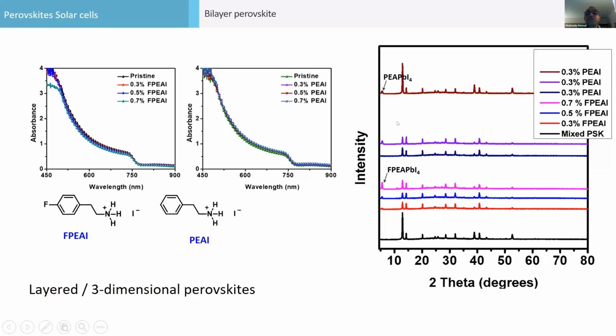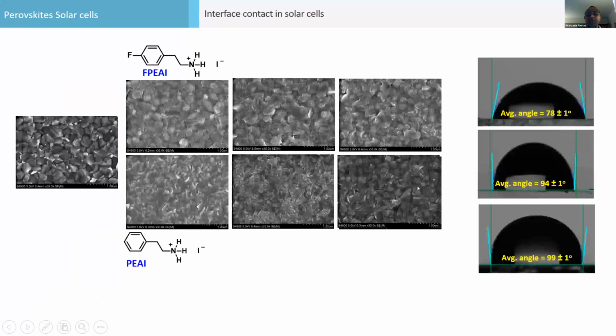Sorry. And also it formed PbI4. If you take phenethylammonium lead iodide, it formed PbI4, and in case of fluorophenethylammonium, it formed a layered perovskite. So these are indications that it formed a layered perovskite here. But what we do is, if you look at the surface topography, how it changes. This is the pristine perovskite, a three-dimensional, let's say mixed perovskite.